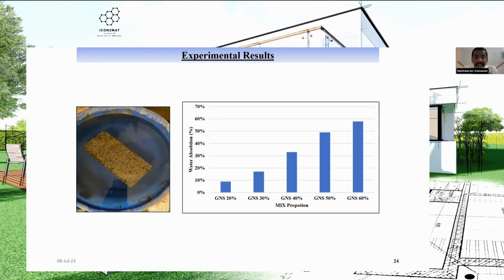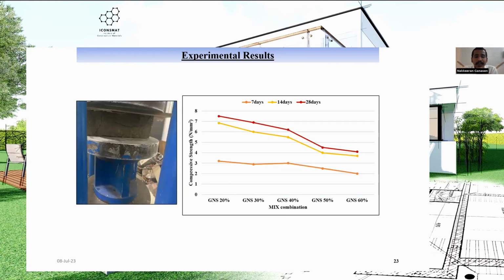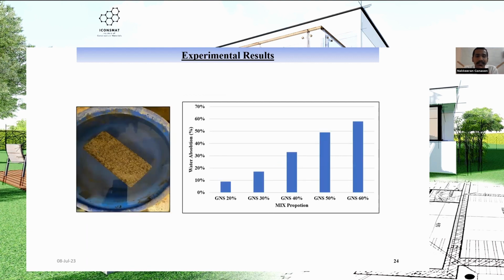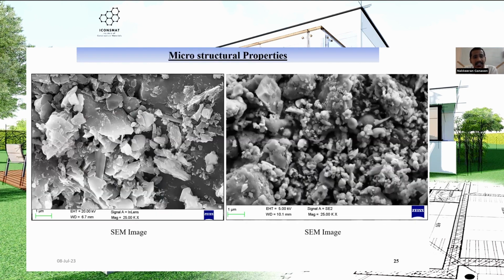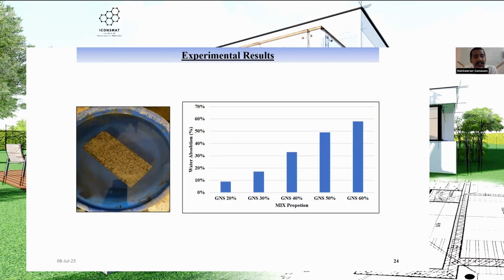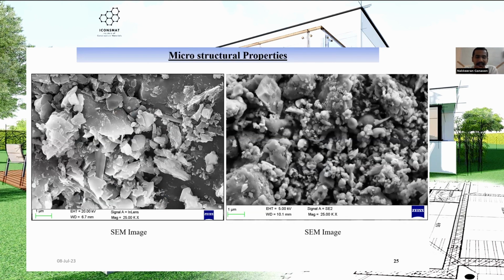While increasing the dry density, the water absorption also increased. So we plan to stop at this optimization: the GNS replaces 30% of the fine aggregate, the sand. The brick is made totally of waste material like fly ash, hydrated lime, and the GNS, with 10% cement and 10% natural sand aggregate. So the cost of the material is very low. Preparing the material, the total process costs about 8 rupees per brick.